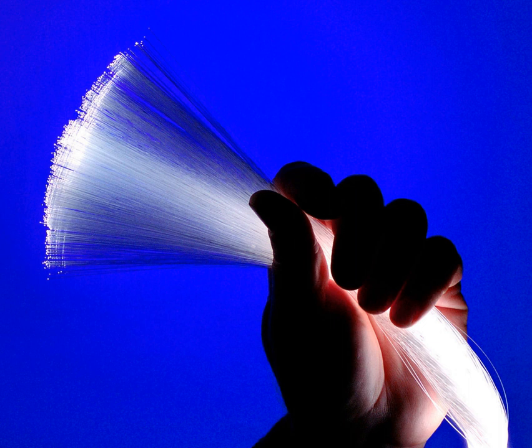A typical single-mode fiber used for telecommunications has a cladding made of pure silica, with an index of 1.444 at 1,500 nm, and a core of doped silica with an index around 1.4475. The larger the index of refraction, the slower light travels in that medium. From this information, a simple rule of thumb is that a signal using optical fiber for communication will travel at around 200,000 km per second. To put it another way, the signal will take 5 milliseconds to travel 1,000 km in fiber.